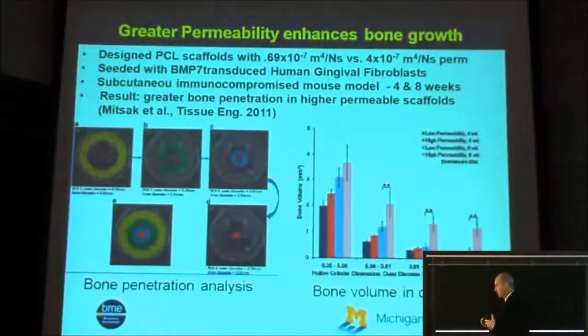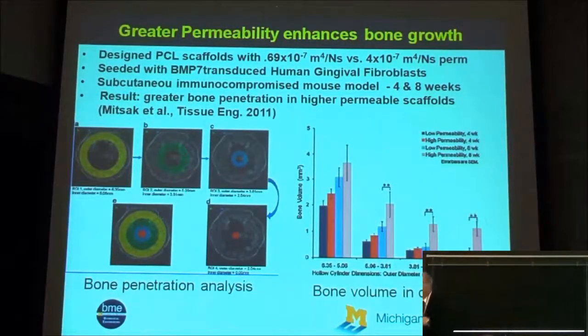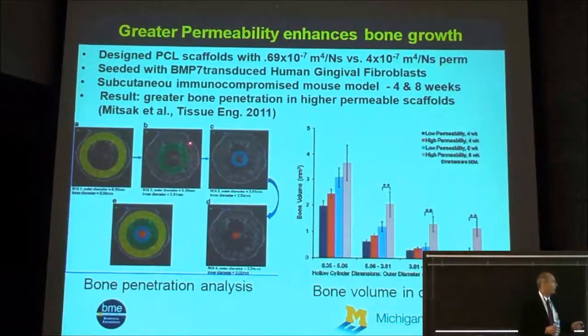So the first thing we want to answer is, we're going through all this process to design pore structures and build them with certain pore structures. Does it really make a difference for tissue regeneration? Specifically, we've designed and built scaffolds with a range of permeabilities, as you can see here. And we wanted to test, does that affect bone regeneration? That's a tissue we're interested in for craniofacial reconstruction, orthopedics, and spine. So this was essentially taking two different scaffolds, both made out of PCL, loading them with BMP7 transduced human gingival fibroblasts and putting them into an immunocompromised mouse model.